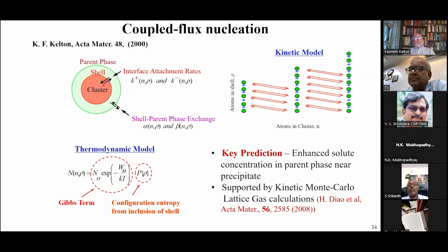So what I did was I developed a very simple model where I looked at the cluster, a region around the cluster, and I looked at atoms moving into and out of the shell region from the parent phase, and then joining and leaving the cluster. The thermodynamic model for this is very simple. You basically assume the Gibbs model, but you have to include an entropy term because you're taking atoms from far away and you're localizing them to a shell.